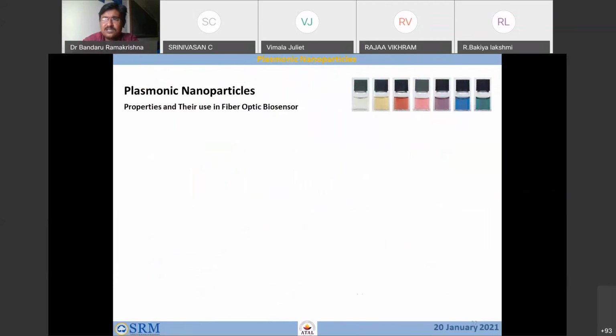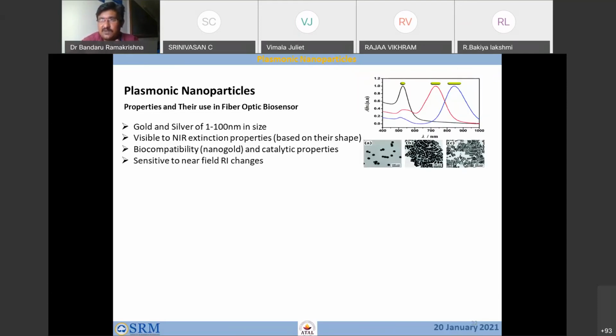Next, the importance of nanoparticles here. Why don't we use nanoparticles in conjunction with optical fibers? Yes, we can, as we have already seen the SPR technology where the thin film is coated. It is a two-dimensional structure. Why not go for nanoparticles or dots instead of a two-dimensional structure, something very small in size, zero dimensional, like quantum dots? What is important here is that plasmonic particles, such as gold or silver nanoparticles, appear in different colors because of their size. Each different particle, for example a sphere or a rod or a long rod, has different absorption characteristics. However, these nanoparticles are very sensitive to environmental changes. For example, if any other particle comes and touches the nanoparticle, the absorption characteristics of the nanoparticle will slightly move. So this can be used for sensing applications using optical fibers.